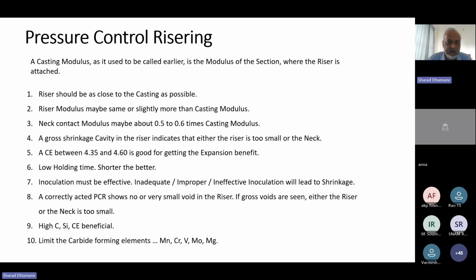I think this point is worth repeating again and again, that neck modulus should be in the range of 0.5 to 0.6, sometimes 0.7 also. But with more neck modulus, we run into the risk of neck shrinkage. The fourth point is gross shrinkage cavity in riser indicates that either the riser is too small or the neck is too small. This happens in the case of steel casting most of the time.